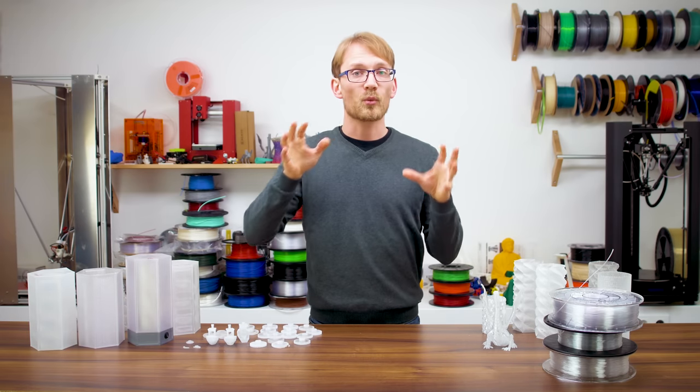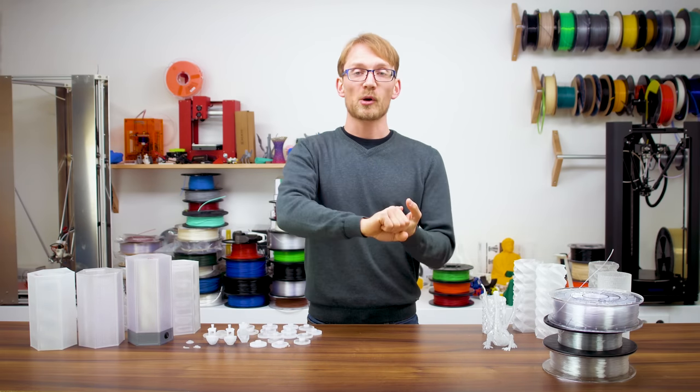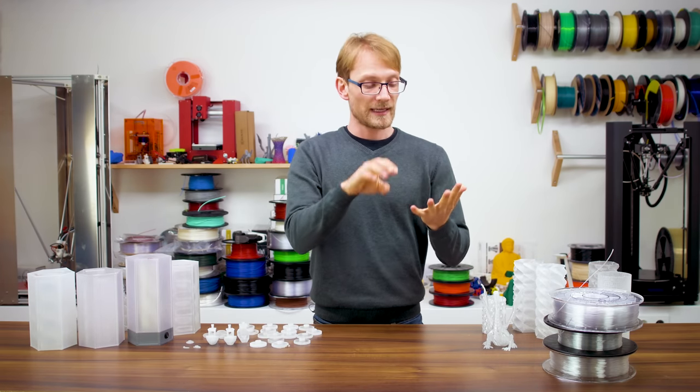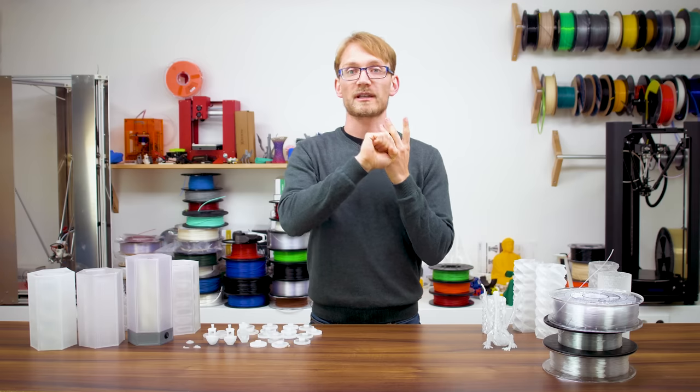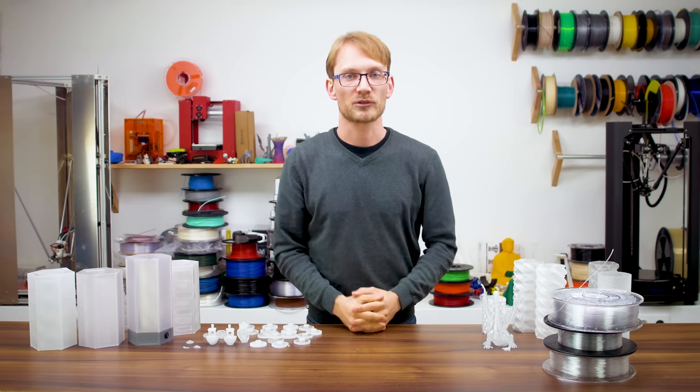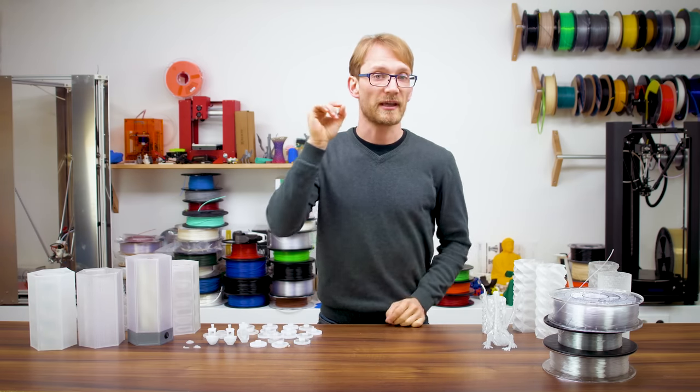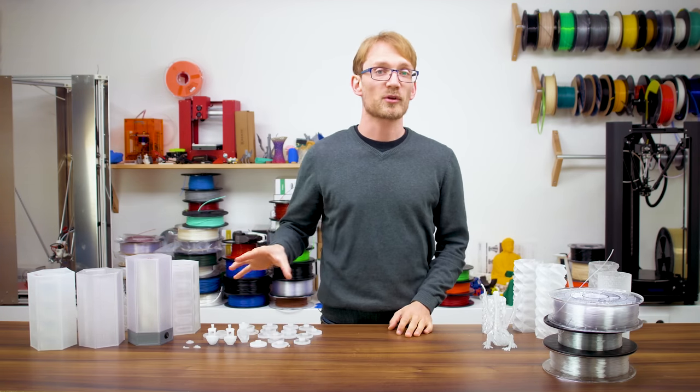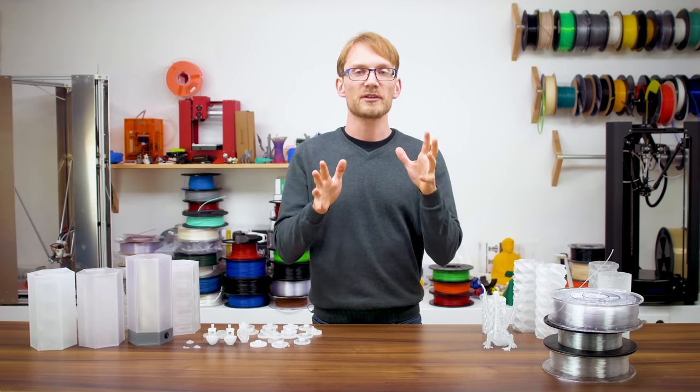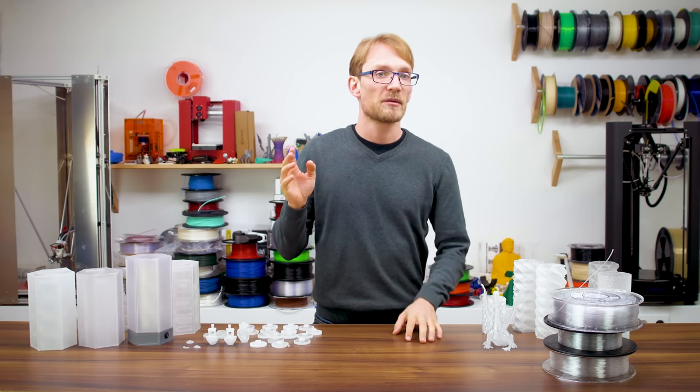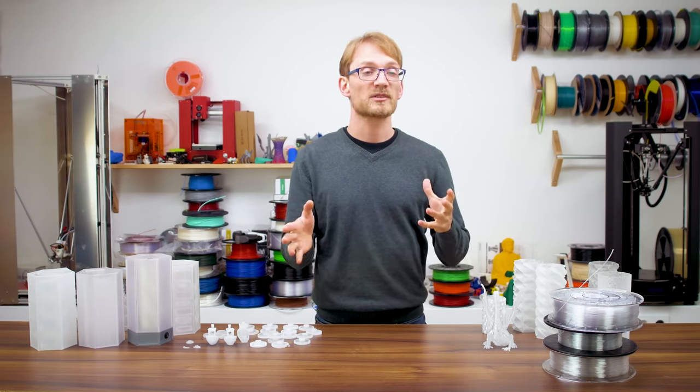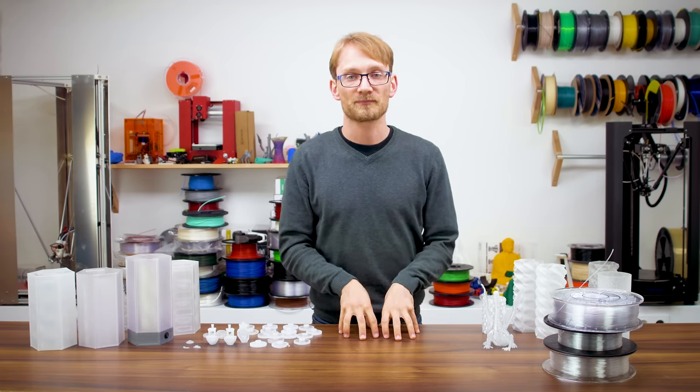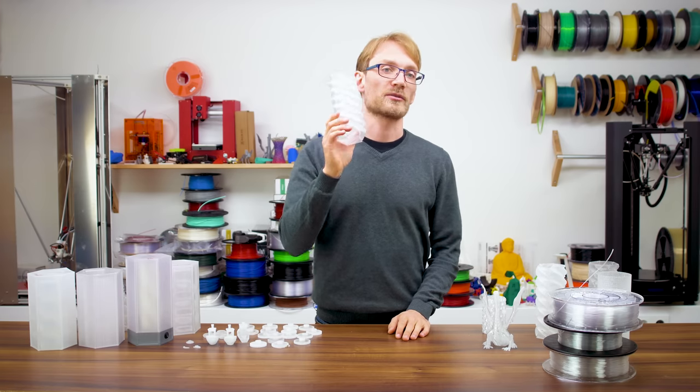So to recap with solid prints: With polyester filament, use a low layer height, 100% infill obviously, and tune the extrusion multiplier so that you're getting maybe a tiny bit of overextrusion. Higher temperatures can help, but it's really easy to cook your filament that way. Post-processing prints to improve the surface is hard to do right, at least with heat. Maybe those thick coatings can help here. I've played around with spray-on clear coats before, but they didn't improve things at all. Awesome, let's check out how these parts are printed.